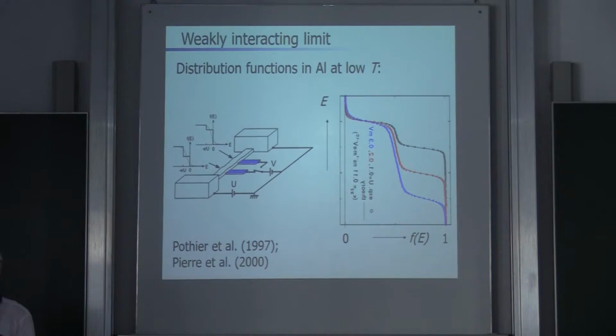Actually, this distribution, which you inject into a normal metal by transport, can also be measured directly at low temperatures in these old experiments. What you see here are tunnel junctions to a normal metal, and these ones here are superconductors. By tuning the voltage level of the superconductors, because they have this very sharp edge for quasi-particle transport, they can really measure the distribution functions of the electrons in the normal metal at these positions. And as a function of the delta U over this bridge, they do not see something close to a Fermi-Dirac distribution function. No, they see a double step of electrons which come from this side and electrons which come from that side.